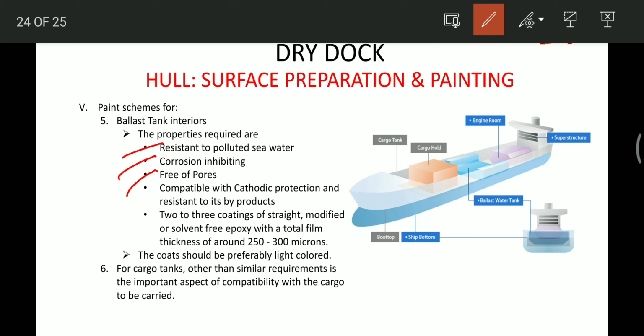2 or 3 coatings of straight, modified or solvent free epoxy with a total film thickness of 250 to 300 microns. The coating should preferably be light colored. And for the cargo tanks, other than a similar requirement, the important aspect is compatibility with the cargo to be carried. So for the ballast tank and cargo tank, it is very much similar: 2 or 3 coatings of straight, modified or solvent free epoxy with a total film thickness of 250 to 300 microns. But over here for cargo tanks, one extra thing is added, that it should be compatible with the cargo which is carried in the tank.